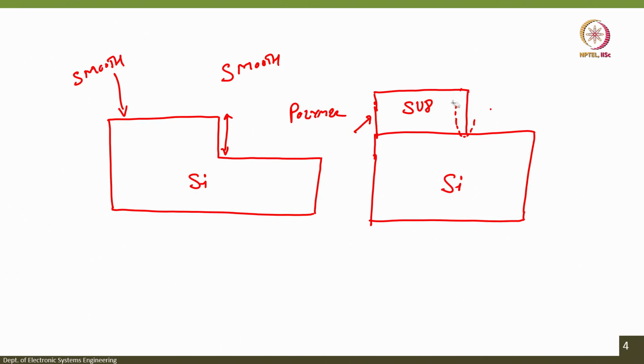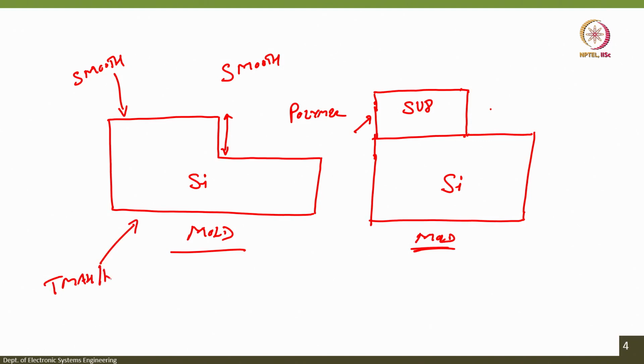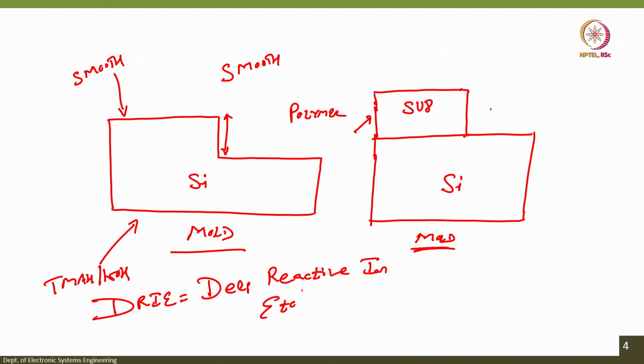The second thing is the way the silicon mold is created. This is a standard photolithography technique where you have exposure, you have bulk micromachining, and you can create a mold. This is an alternative way where you do not have that. So, again silicon, when you do that, right. So, I told you that you can use TMAH or KOH, but an alternative technique is to go for the DRIE, which is called deep reactive ion etching, deep reactive ion etching. Okay.